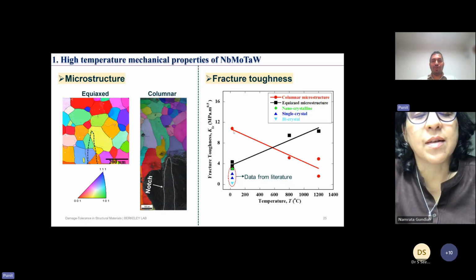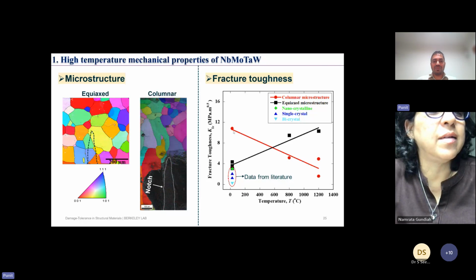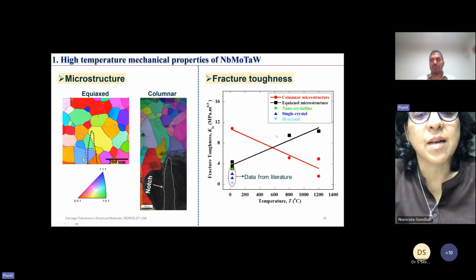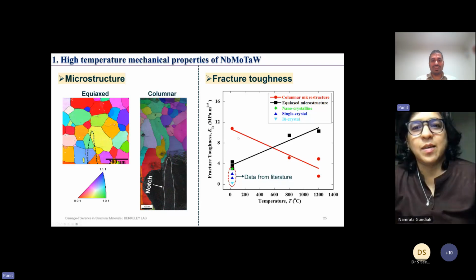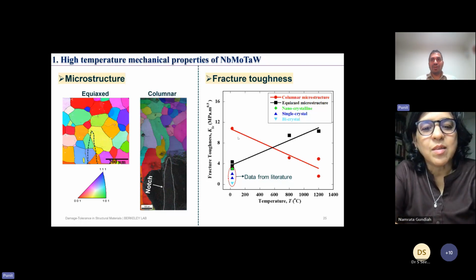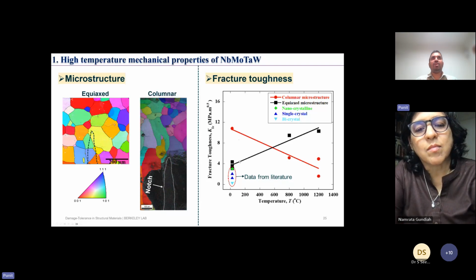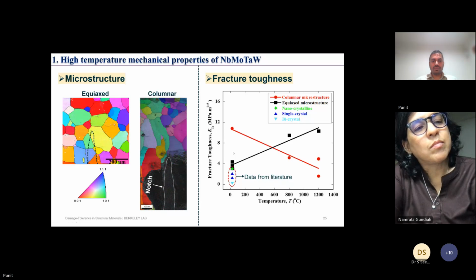We were only able to say post facto that this sample is for this condition. So that's why we ended up doing multiple tests for certain temperatures, but for certain temperatures we did not have multiple tests. But with respect to the values equilibrating when you keep this material for a longer time, there was one basic difference in terms of the TEM experiment we did.